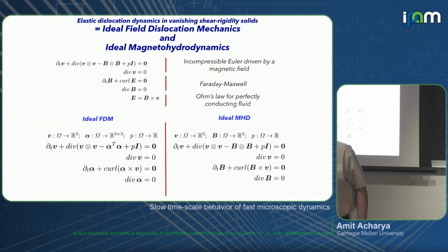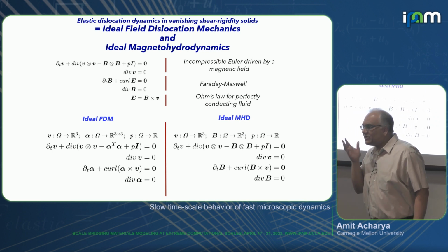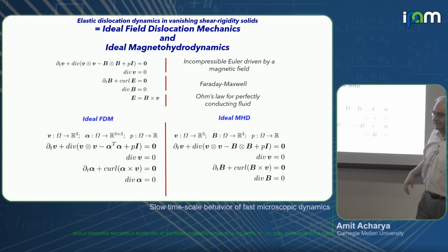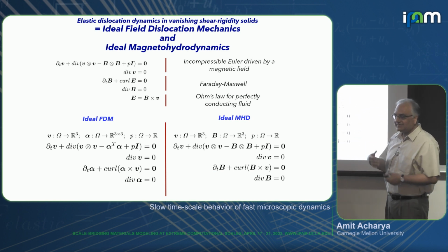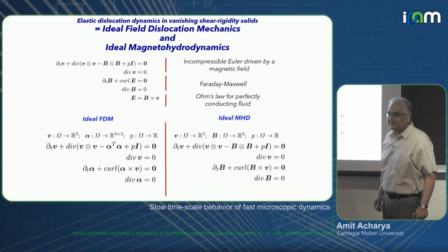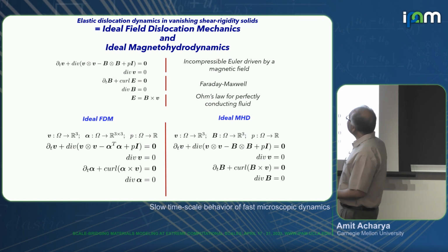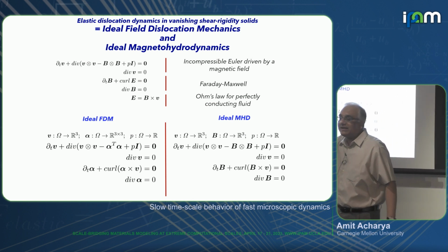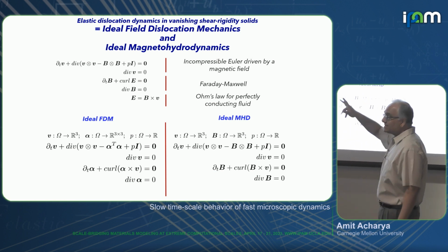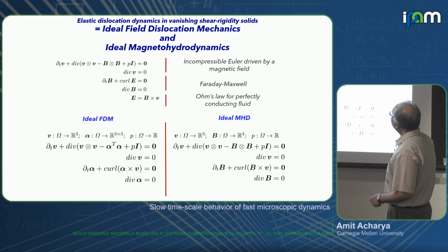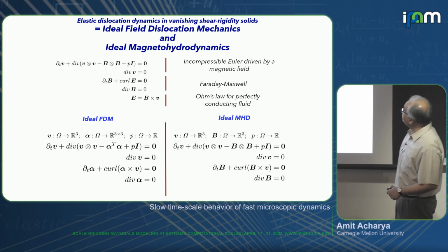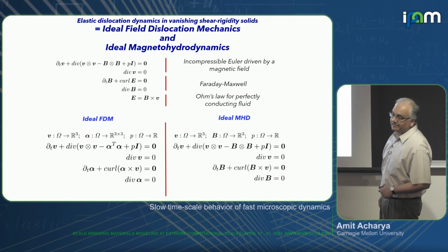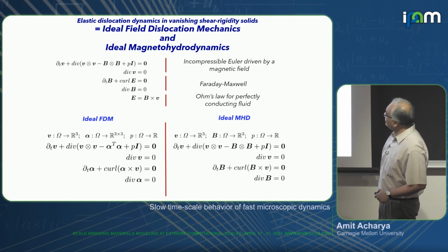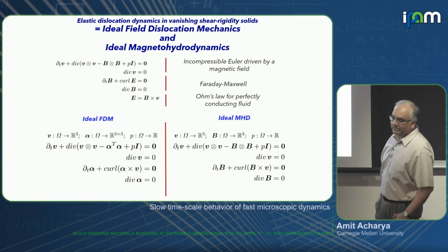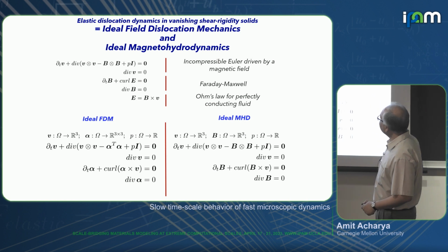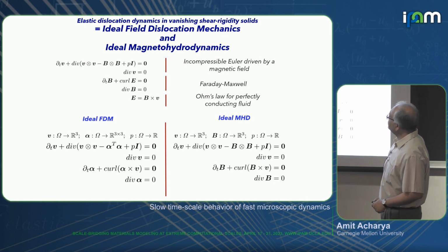And then, okay, so fluctuations, and you don't have to go looking for connections through post-processing to links with fluid dynamics and turbulence here. So this is, so I'll call this, so suppose you forget the relative velocity of the dislocations with respect to the material, just keep the material velocity, that little v guy, and then this, okay, this is ideal magnetohydrodynamics. So what is that? That's incompressible Euler, magnetic field, and in Ohm's law, basically, for a perfectly conducting fluid, okay? So these are Maxwell, this is Euler pressure driven by the magnetic field.